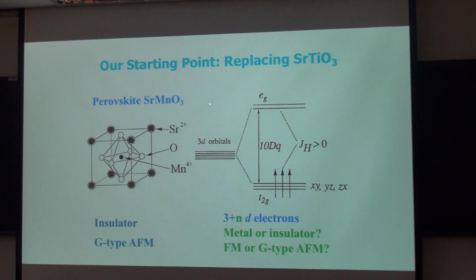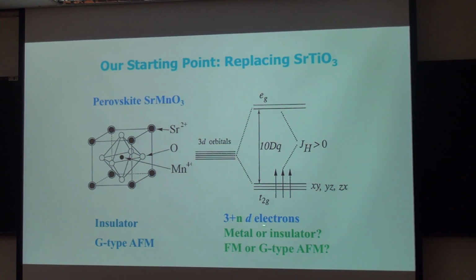The first example is strontium manganese oxide, which is a parent compound of the colossal magnetoresistive manganites. This cubic perovskite has a quadrivalent manganese, which contains 3 localized t2g electrons. And these t2g electrons couple antiferromagnetically in the bulk form, and it is an insulator. Therefore, we can ask if there is a charge transfer from the polar material at an interface. Therefore, we can realize a 3 plus nd electron system. And we will ask ourselves, what is the consequence on the electronic structure, metal or insulator, G-type antiferromagnetic or ferromagnetic